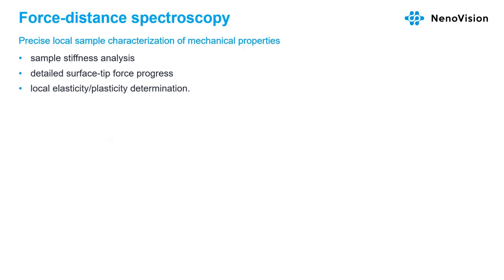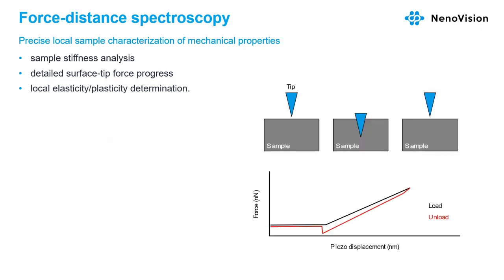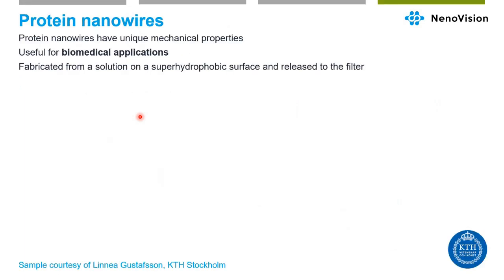Another technique for analysis of local elastic properties is force distance spectroscopy. The stiffness or the sample adhesion can be measured from these curves. The area is first localized and the tip navigated to this area. Then we use the force to push into the sample while choosing the depth. And then we go away from the sample. So we see the load and unload, so we are able to know the stiffness from the slope of the curve, and the adhesion. So there is different information which we can get from the spectroscopy.